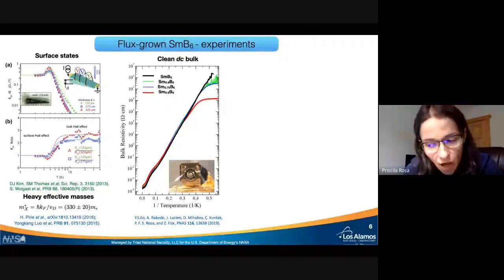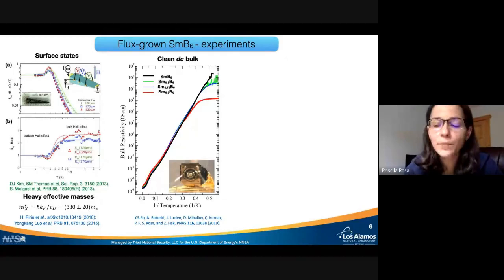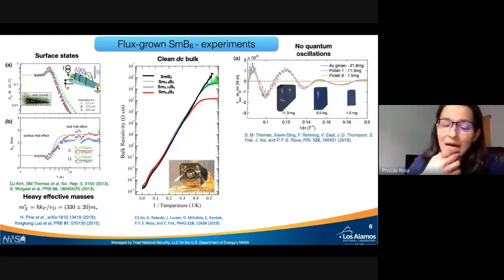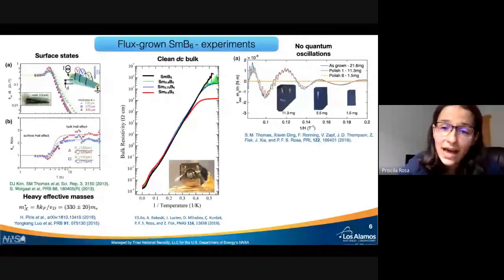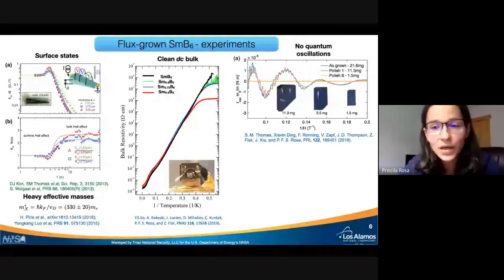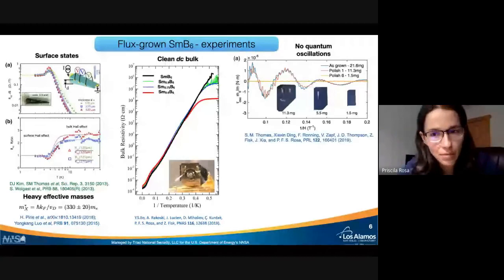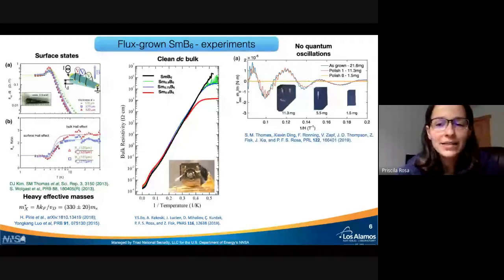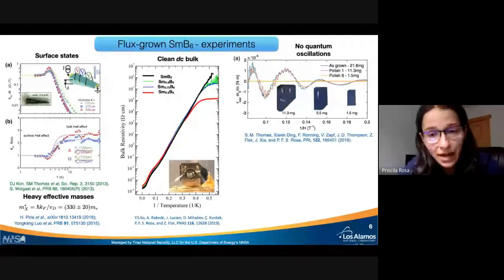But we decided to take another look at this material and at the fact that it may generate quantum oscillations. And we found out, and this is my next figure, that quantum oscillations actually, unfortunately, disappear as we polish the sample down to a very thin slab. And this is very unfortunate because these samples are grown by a technique that involves a third element, and this third element is aluminum. And there is incorporation of aluminum in these crystals.